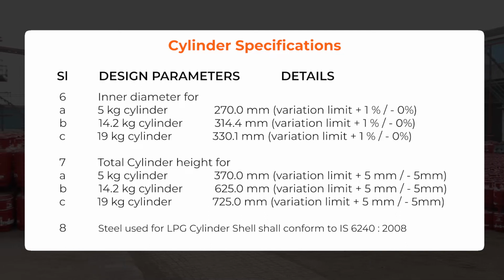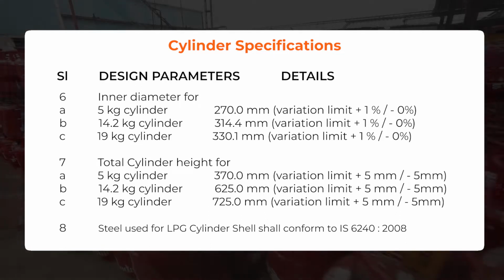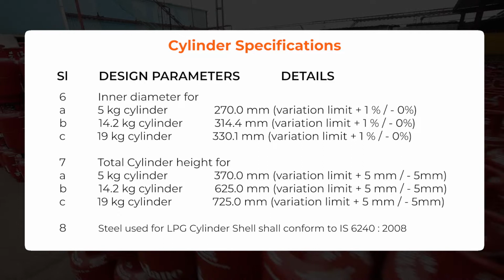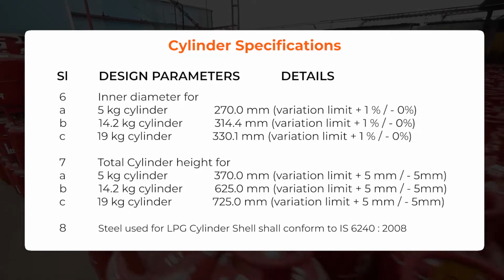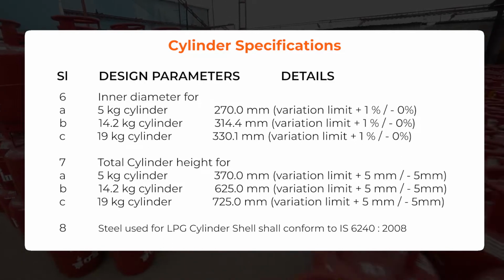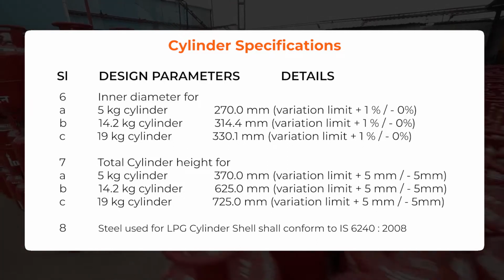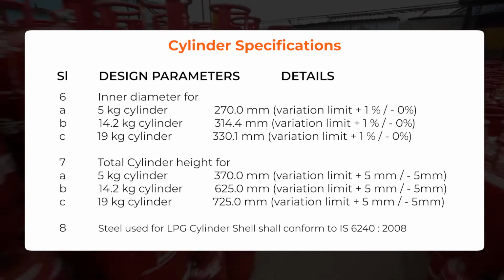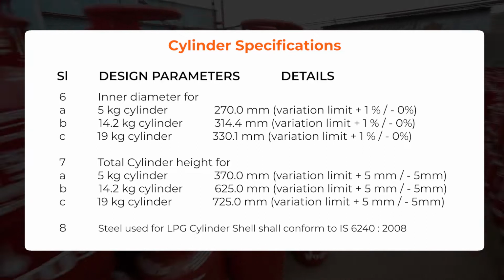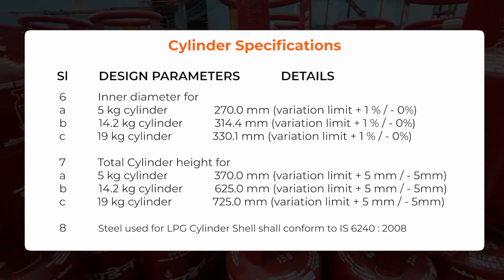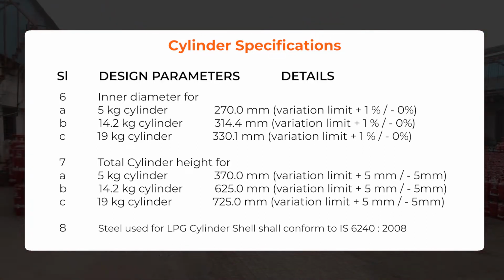14.2 kg cylinder 314.4 mm. Variation limit plus 1% minus 0%. 19 kg cylinder 330.1 mm. Variation limit plus 1% minus 0%. Total cylinder height for a 5 kg cylinder 370.0 mm. Variation limit plus 5 mm minus 5 mm.